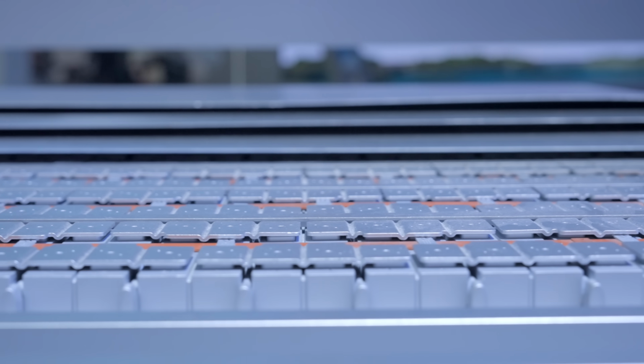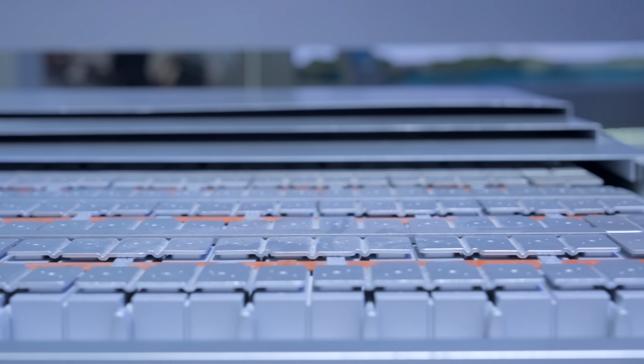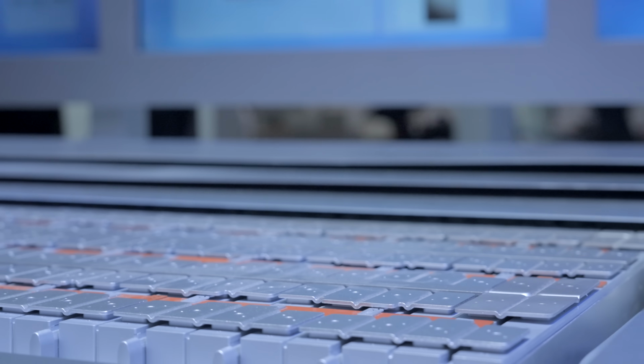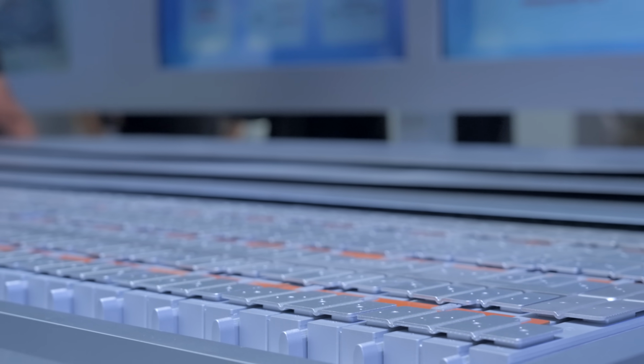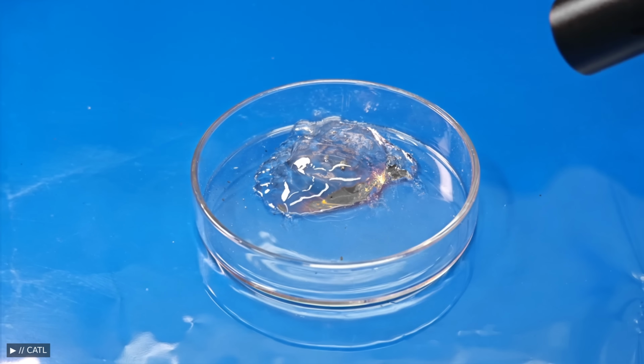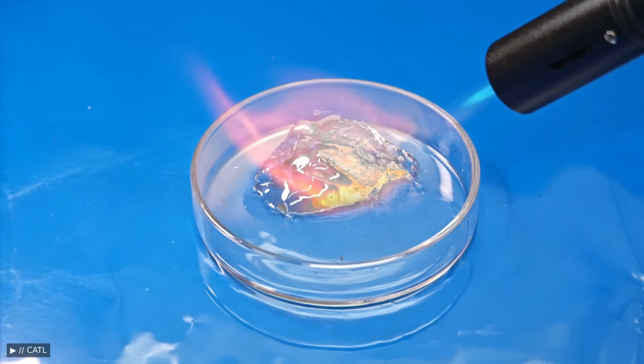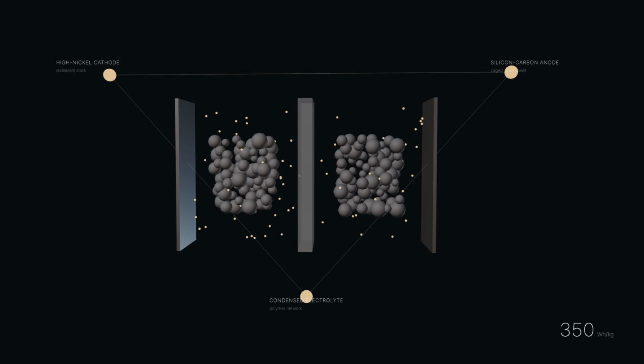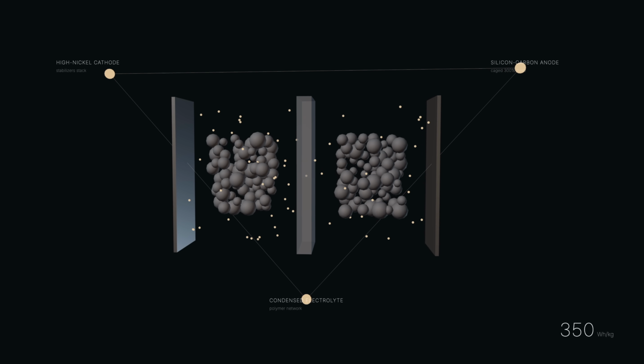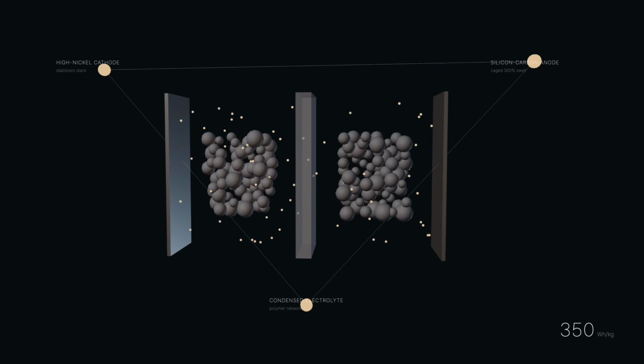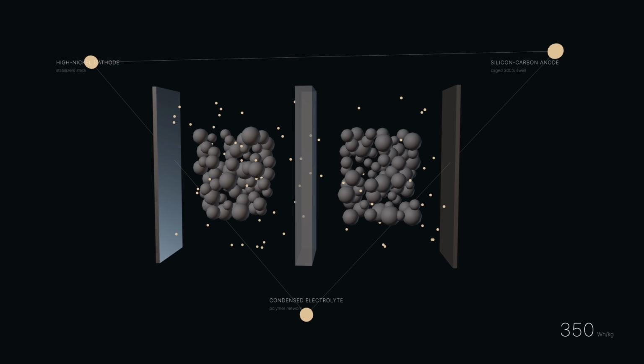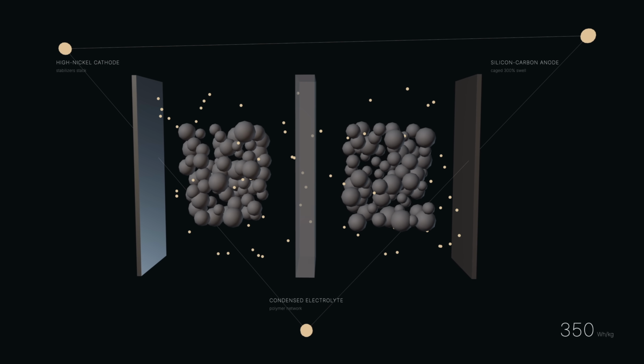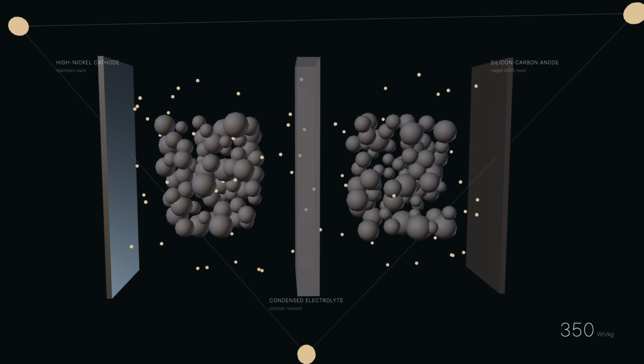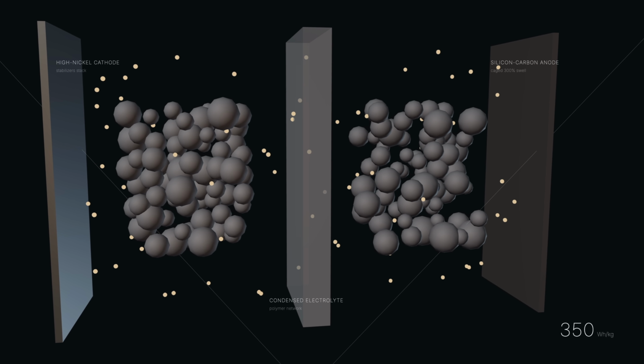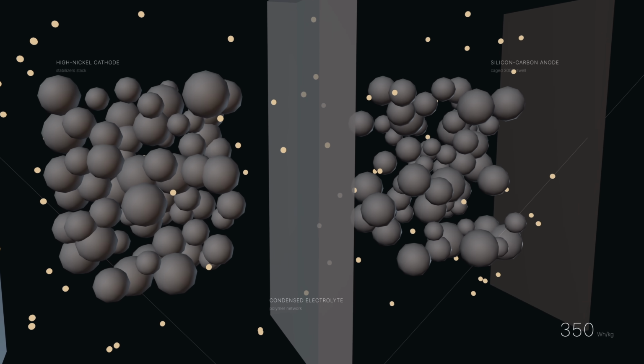Now, running a very high nickel cathode and a silicon-rich anode together in a conventional liquid electrolyte cell would be like a fight against physics. The cathode runs hot, the anode breathes, the electrolyte degrades in the middle of both. The condensed electrolyte is what makes this pairing stable at scale. The polymer network holds its shape as the silicon swells and contracts, and the absence of free liquid lowers the thermal risk of running the cathode at the edge of its stable window. So the three pieces, high nickel cathode, silicon carbon anode, and condensed electrolyte, are not three separate improvements stacked next to each other. They are a single, tightly coupled system where none of them work at scale without the others.